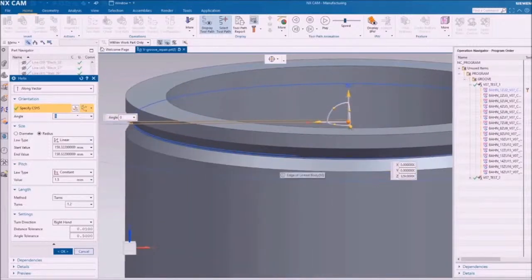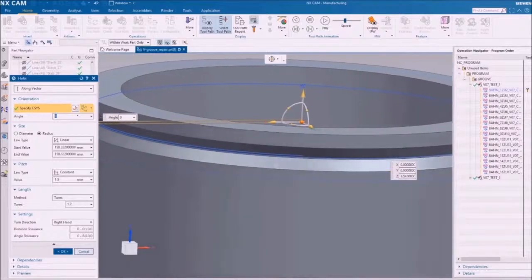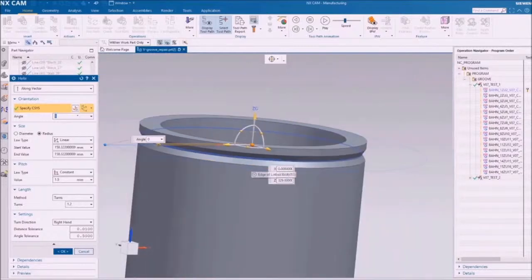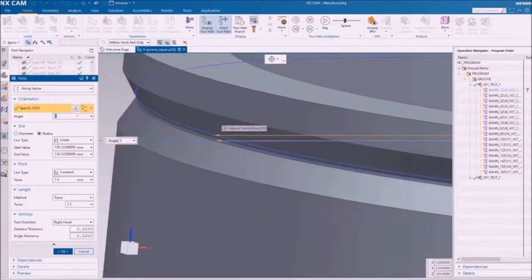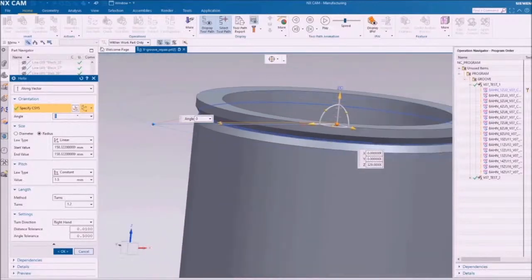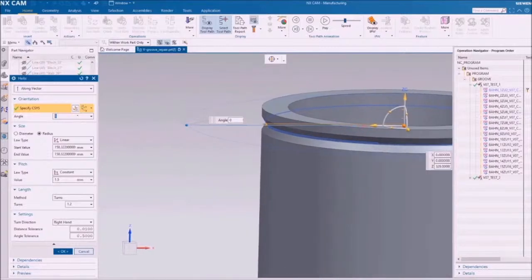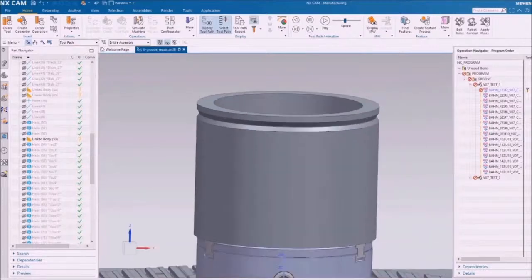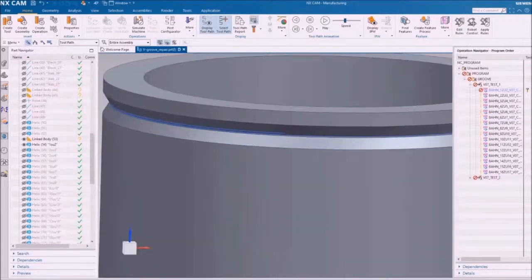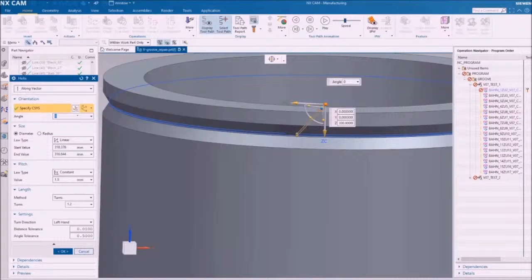A spiral movement of the cold spray nozzle around the cylindric component presents a suitable driving strategy. The starting point for the repair process is placed in the center of the groove because it is the steepest and requires the most material, that is, the most repetitions of the deposition path. Starting from this point, the tool is moved on a helix-shaped path.